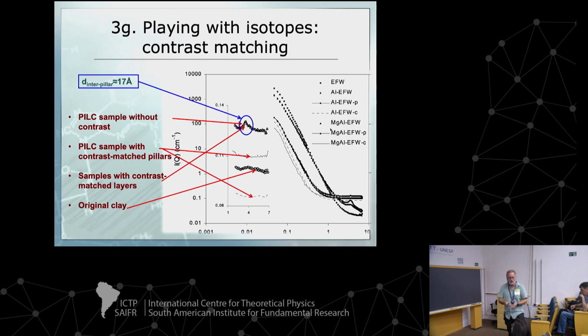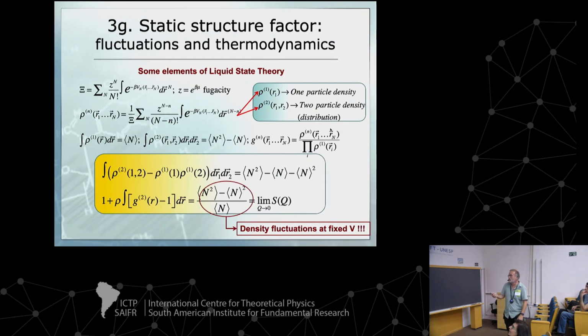As I mentioned, sometimes things are a damnation, sometimes are a blessing. This negative scattering length of hydrogen is bad, but thanks to that, you combine heavy water, and you end up having a material which can match almost anything, as long as you can use water. For some systems, you cannot, right? But you can play around with isotopes, obviously.